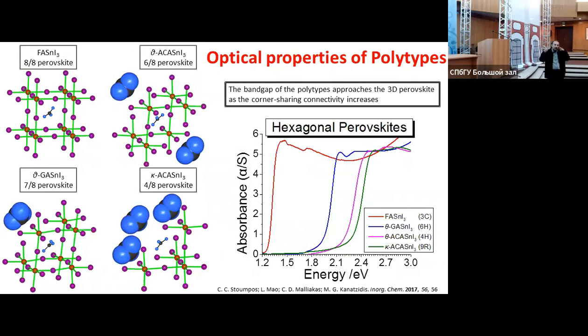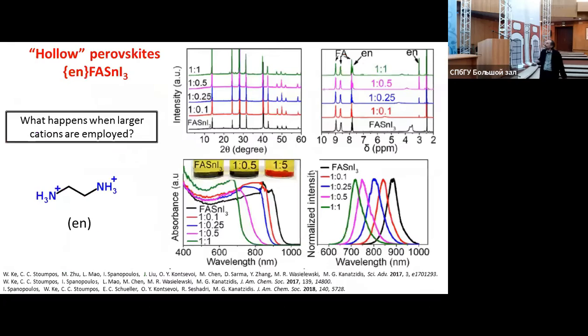And if you conceptualize how this is happening, essentially you get a perfect perovskite and you start removing metal ions and replacing them by the large cation. And this has a strong impact on the optical properties. This is the perfect perovskite, and you see how much you change the optical properties when you go through the several cations. So this may or may not be interesting. These materials have not been seriously looked at, but we know that they have some similar characteristics with the other perovskites. And then we end up with this strange cation, ethylene diammonium.